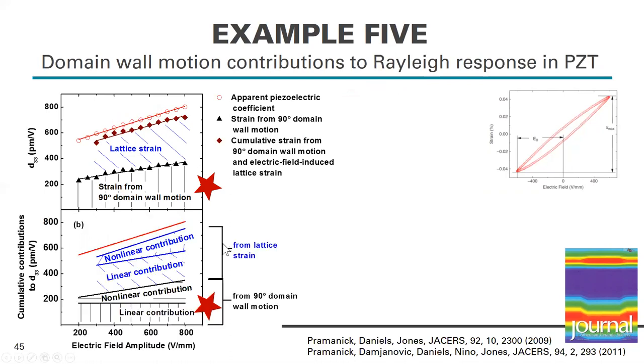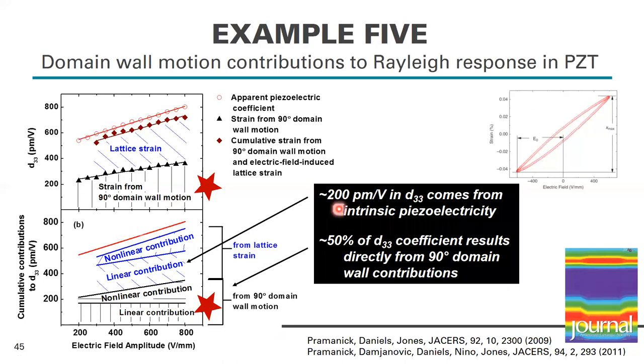You can break that down even further, and you can look at the linear and nonlinear contributions. And we're not going to dive too much more deeply into this, but I'd encourage you to read the paper if it's of interest to you. The main messages are that only about 200 of this macroscopic coefficient comes from the intrinsic piezoelectric effect, and about 50% of the coefficient resulted directly from these extrinsic or domain wall contributions.